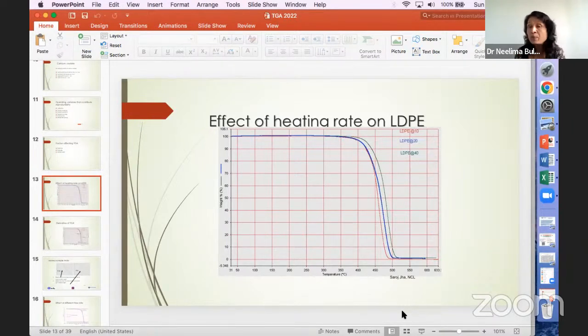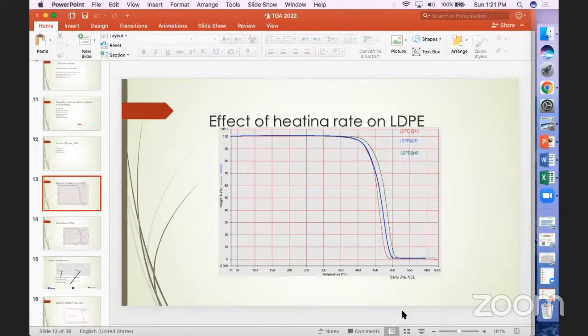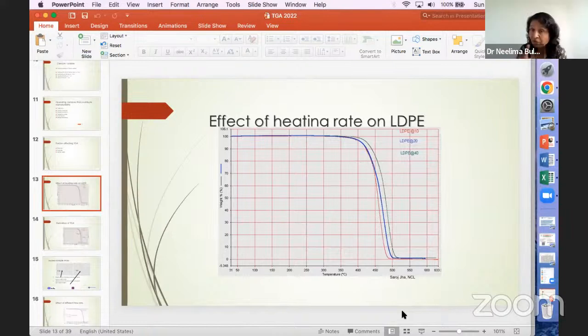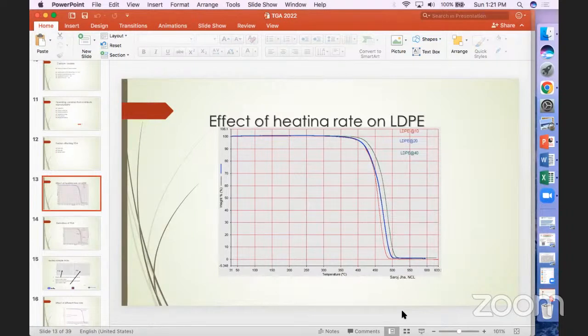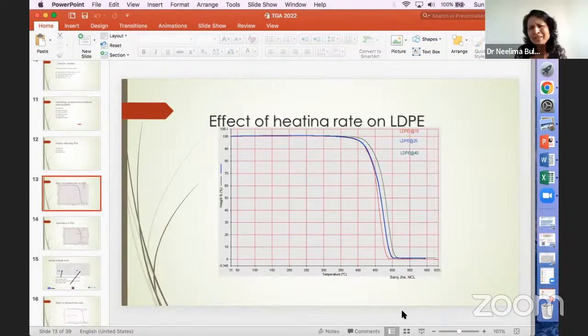That's what I see. If your material is not getting cured in the melt, and if you are heating the material and you get the first Tg but you are not getting the Tg in the second heating, does it mean that your material is getting cured, getting cross-linked during heating? That could be, yes. Polymer is a very complicated system. Thank you, madam.